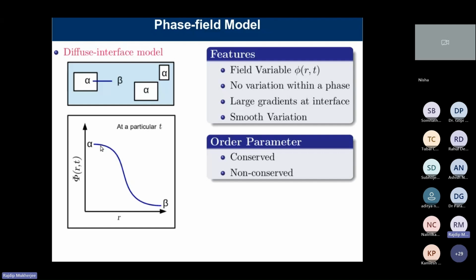This phase field model is called a diffuse interface model, and you can see there are some alpha particles in a beta matrix. If you go through the interface between the alpha and beta, in the plot below you can see this is a diffuse interface, a region where the composition and other properties change in a diffuse manner. This change in composition and properties is captured using field variables, phi. These may be the composition or the density. These are called conserved field variables.